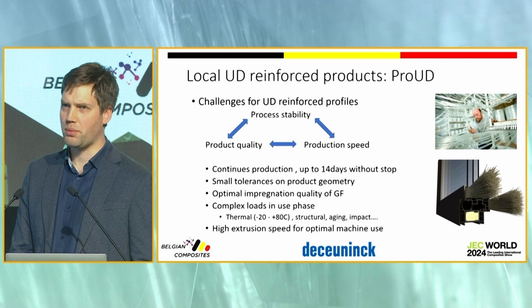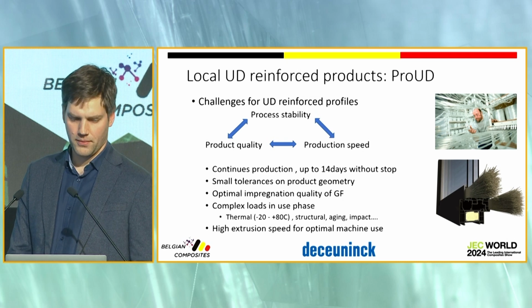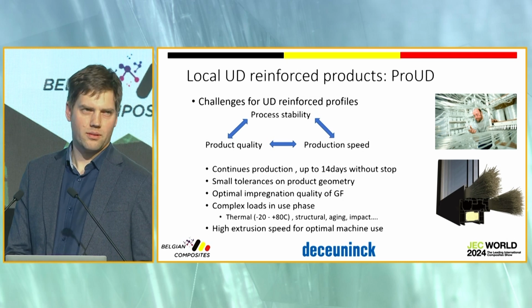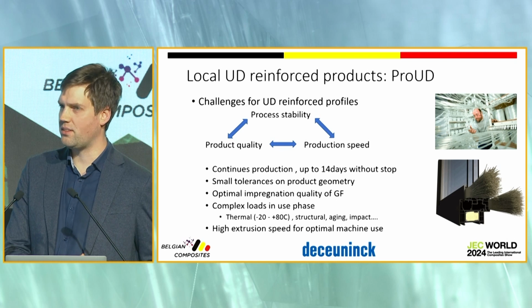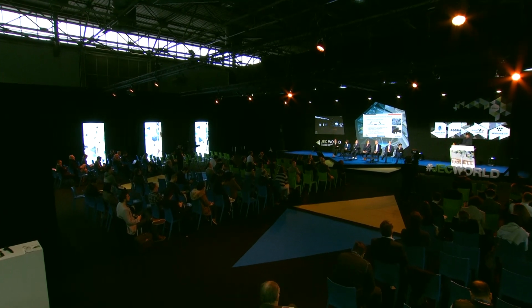And you cannot imagine how complex the load cases are for a window profile. First, you have the temperature loading: in the winter, -20, and in the summer, even up to +80 degrees. But you also need to keep up the structural integrity, holding up triple glazing windows, but also a large wind load. Storms often occur, and of course your window cannot fail. After that, you also have the aging of the PVC and of the profile, and we give a 20 years guarantee. It even goes up to 40 years in installation. And at the end, you also need to have a good impact stability of the profile.